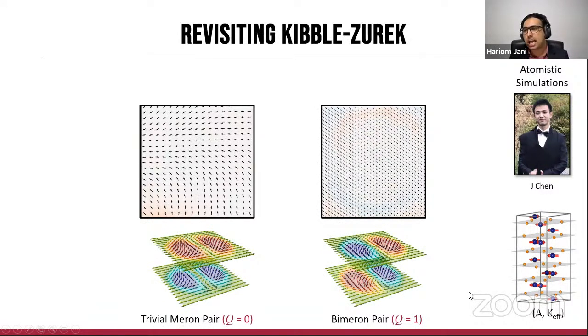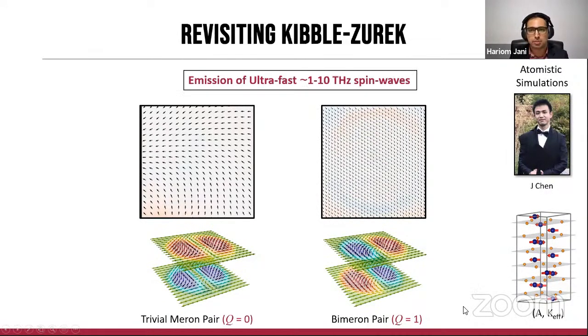And when we analyze the kind of dynamics that they exhibit, this is almost in the terahertz regime, and the annihilation of a topologically non-trivial entity results in these explosive emission of spin waves, which can then be used for any number of exciting spin sources, etc., on chip if we were to actually capitalize this. So this is like the first theoretical indication of something like this, and therefore all this is possible with the topological textures that we have been able to stabilize in the system. And all this happens at ultra-fast timescales.